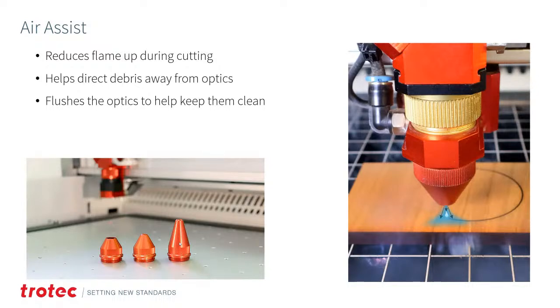Another thing is the nozzle that comes with the laser or with the air assist. You always want to use your nozzle if you have air on. It can actually damage your lens if you have air turned on and you don't have the nozzle in place. A lot of people don't understand that, because what happens is you get a vortex effect. That vortex, like a tornado, if you will, comes down when you're not using the cone. And if you don't have a cone in place, it takes dust and debris and pulls it in, like a tornado would suck debris in, and it can actually damage your lens. So if you have air on, you need to make sure your nozzle is in place.